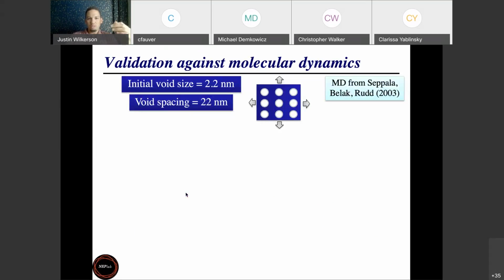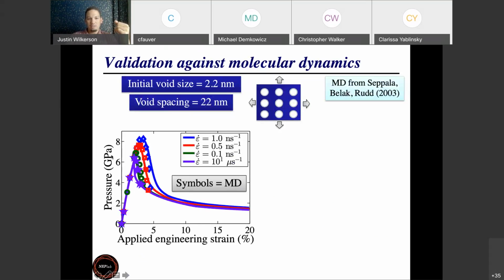We also have some validation against MD calculations. So the symbols here are MD simulations in a single crystal copper with voids of size 2.2 nanometers, spaced equally 22 nanometers apart. And the lines are our predictions from the physics-based continuum theory, and you can see that we capture the rate sensitivity very well, and we capture the softening well as well.